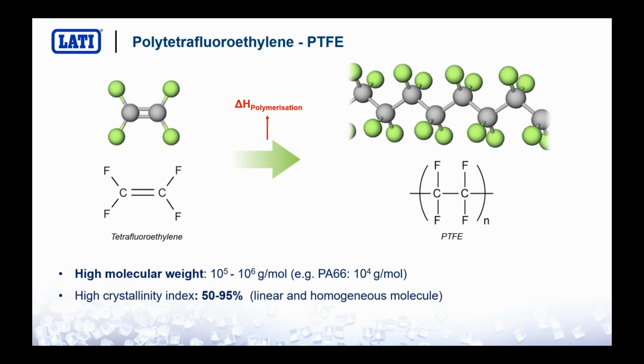You have a very high crystallinity index. PTFE is born with 95%, which is then reduced down to 40–50% during the subsequent processes. But in any case, it is a very highly crystalline polymer because of its nature. It's a very linear and homogeneous molecule, and it's very high density. So it's very heavy, it's very big and it's very crystalline. But this is not enough to understand why PTFE is such an excellent performer.